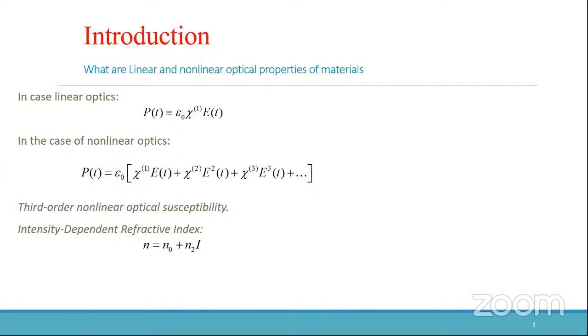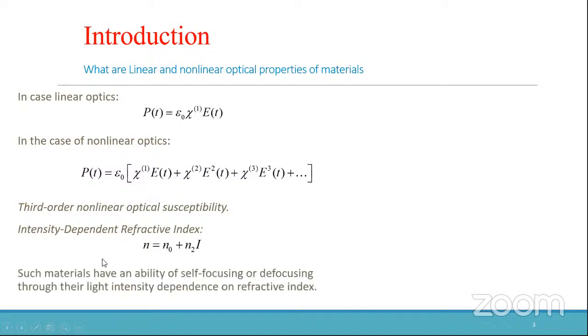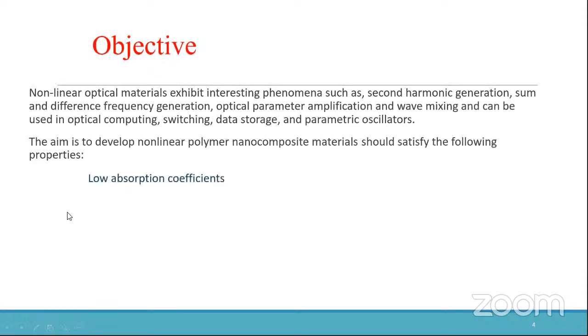When the intensity of illumination is high, the elastic limit of the electron displacement is exceeded and the harmonic restoring force becomes nonlinear, which adds quadratic and higher terms in this formula of polarization. These terms are responsible for the nonlinear effect. The intensity dependent refractive index is given by this equation. Such materials have an ability of self-focusing or defocusing through the light intensity dependence of the refractive index. Nonlinear optical materials exhibit interesting phenomena such as second harmonic generation, sum and difference frequency mixing, optical parametric amplification, and wave mixing, and can be used for optical computing, switching, data storage, and parametric oscillators.